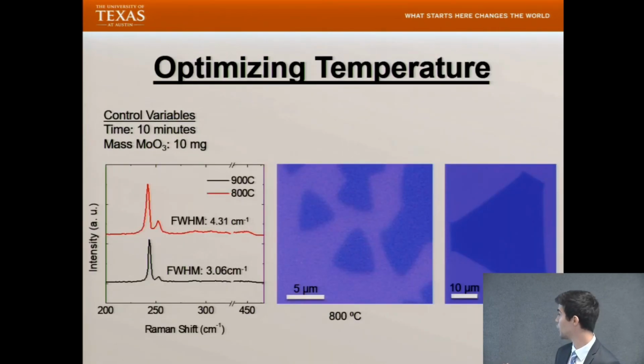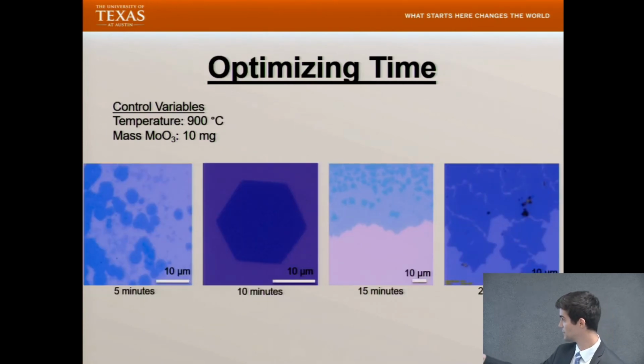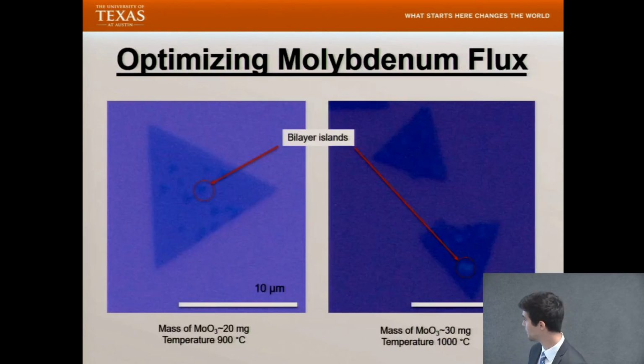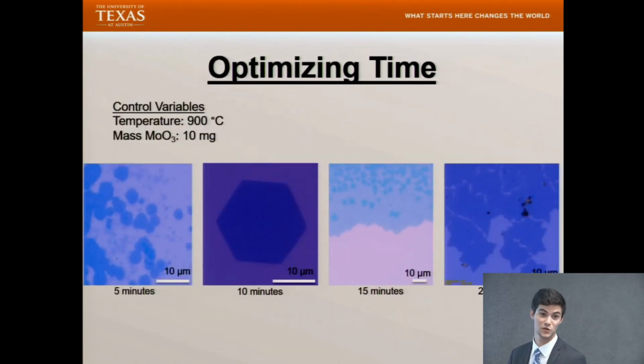You can see that some of these domains are single crystals. So this right here would be a single crystal. This would be a single crystal. How do you know that? Yeah, well, we're able to determine from previous work that all of the single crystals form in either hexagons or triangles. And we're able to tell if it's two crystals, then they'll have formed on top of each other at some point. So by using the photoluminescence data, we're able to determine it would be a bilayer at that point, is what I mean.